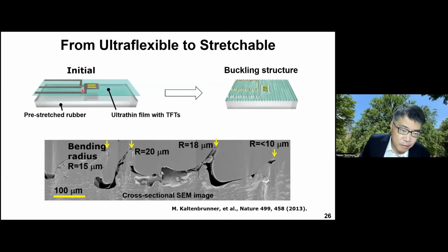So here is the 1 micron thick substrate having the organic devices on the surface. And here is the pre-stretched rubber, and they are laminated together. And after the relaxation of the pre-stretching, the rubber starts shrinking, yet the ultra-thin film doesn't shrink at all. So in that way, we can make the accordion-like wrinkling structure. So this is the cross-sectional SEM image. So here is the wavy structure.